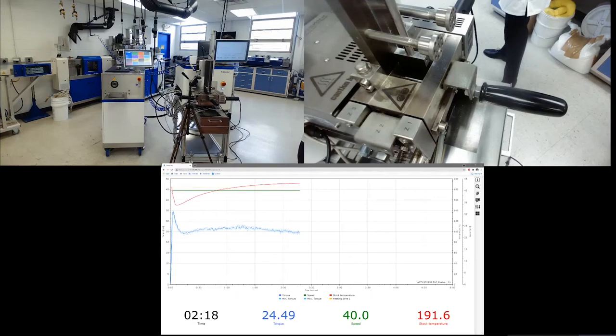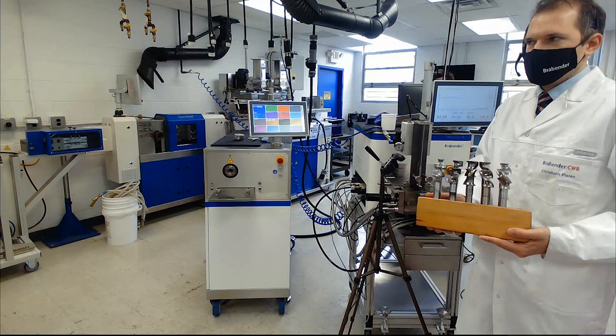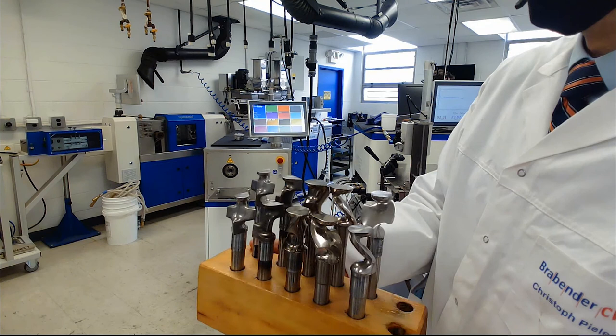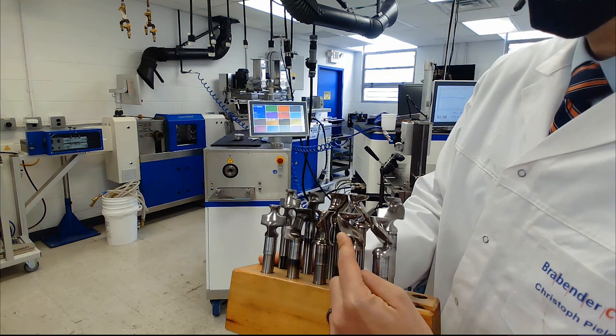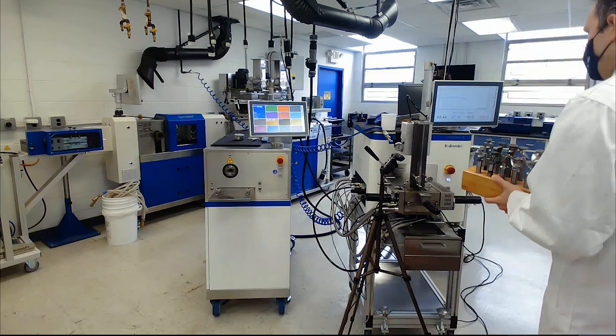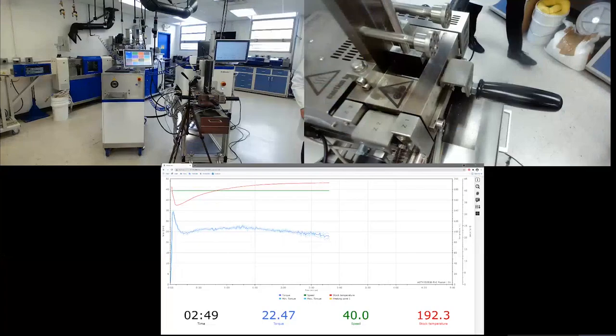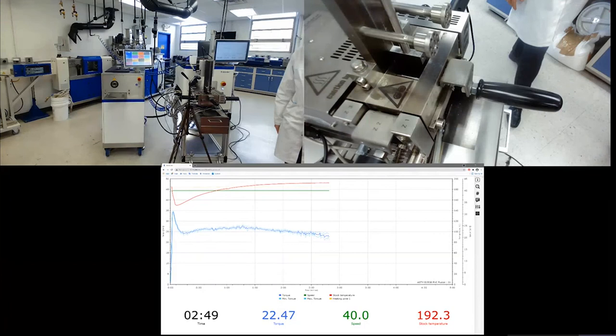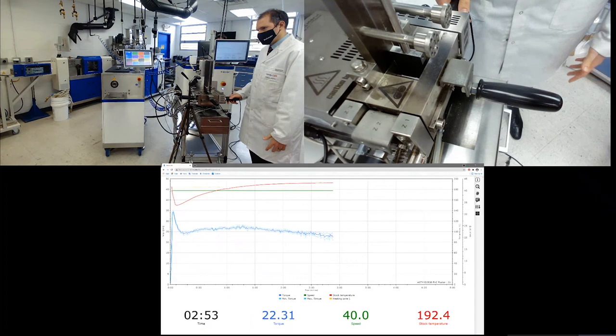If we go now back to the overview camera, you see I have here a sample of different style of blades and they are all compatible with our mixing measuring head, from cam blades for the rubber world, bamboo blades, sigma blades, and the installed roller blades. After five minutes the test will be done and we will get the results immediately associated according to ASTM D2538 for fusion behavior of rigid PVC compounds.